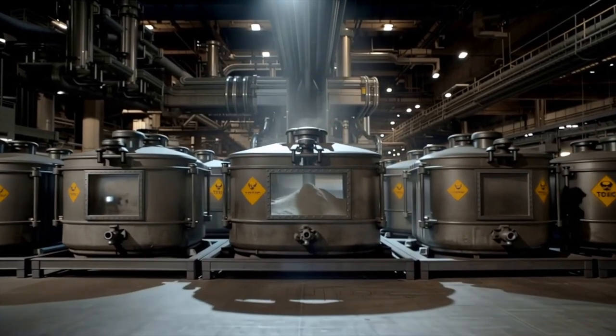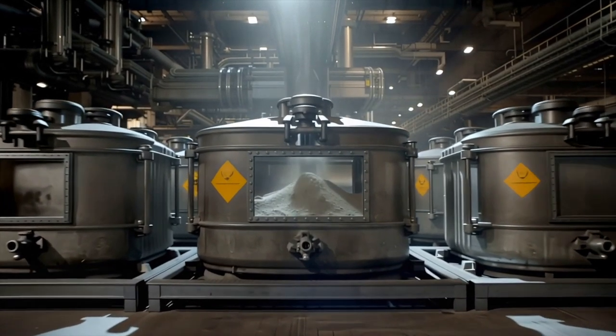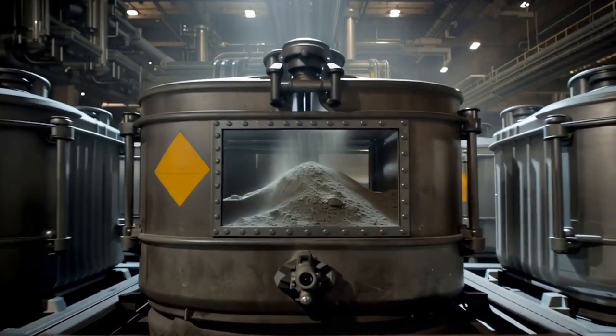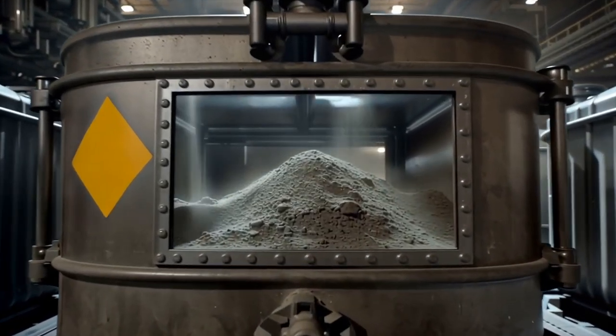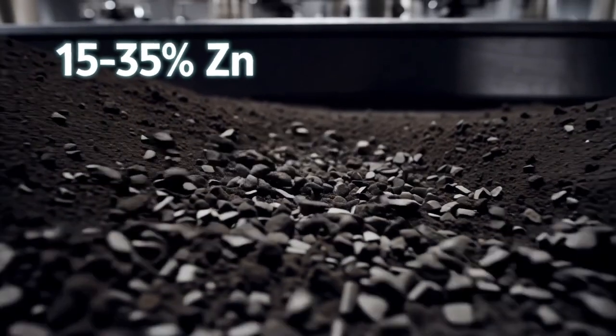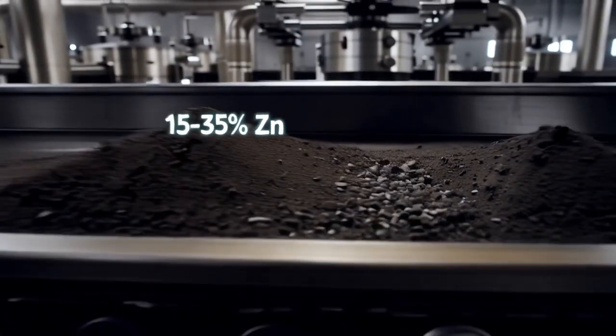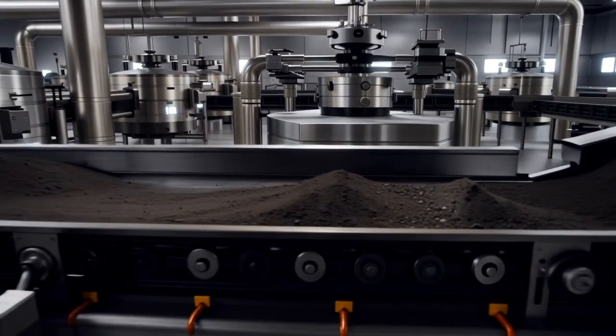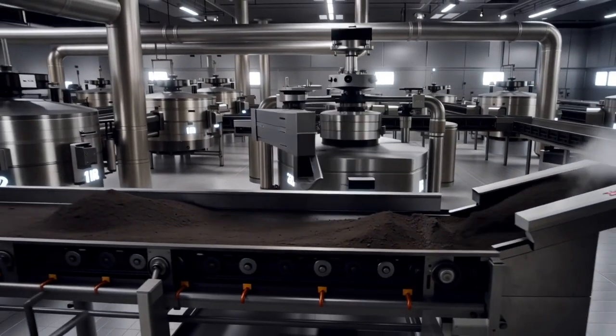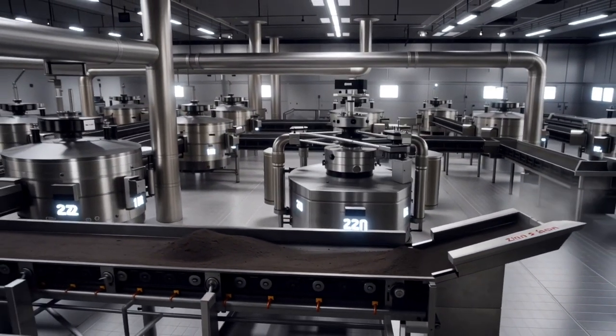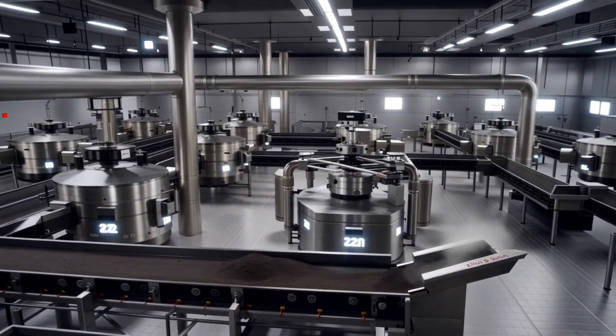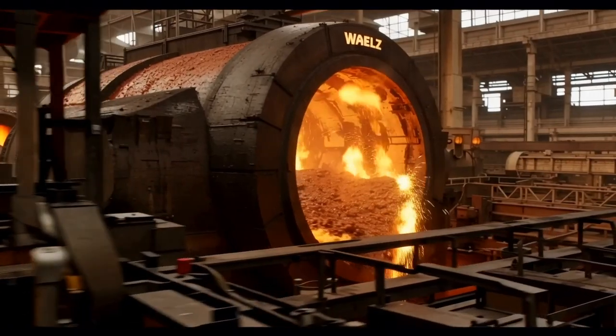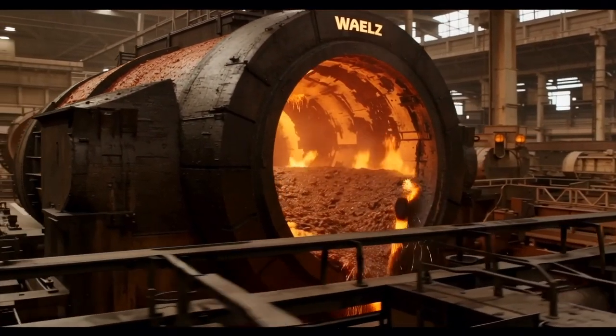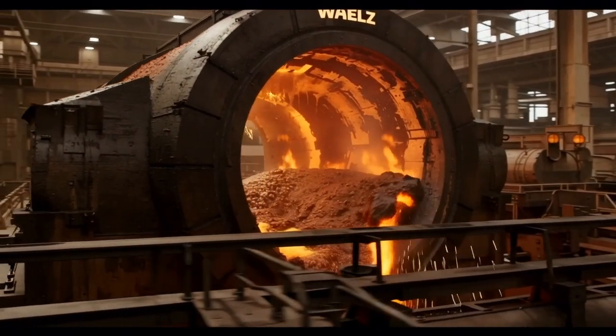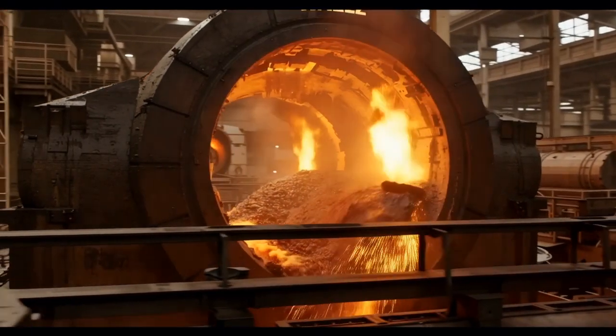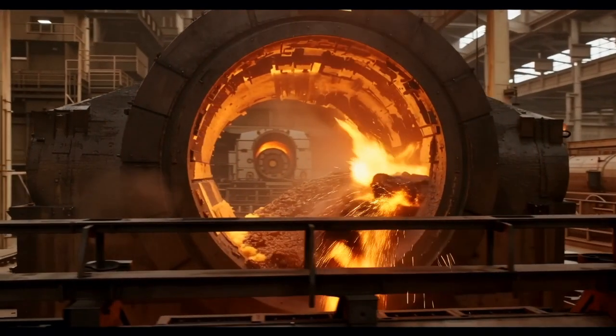Electric arc furnace dust, or EAF dust, is classified as hazardous waste and typically contains only 15 to 35% zinc. At these concentrations, the material is below the threshold required for direct use in zinc refineries. The most widely used enrichment technology is the Waelz kiln, which increases zinc concentration to around 55 to 60%.